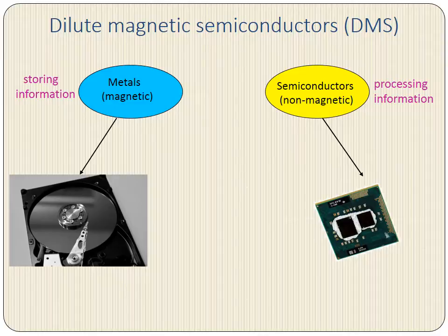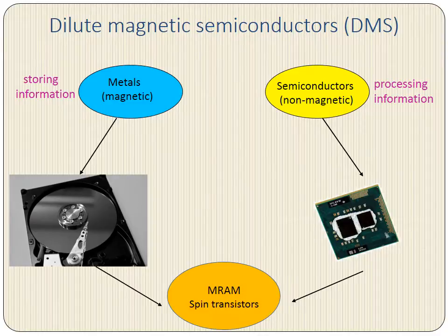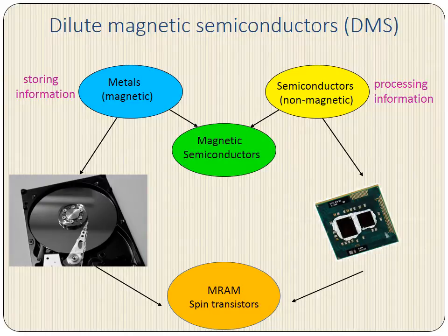Now, to date, we have typically kept these two classes of materials separate within our consumer products. But there is hope to combine them to form new and novel devices, such as magnetic random access memory and also spin transistors. It should be noted that there's been a little more success in creating MRAM over viable spin transistors. However, integrating magnets and semiconductors hasn't been straightforward. A fundamental obstacle has been the impedance mismatch between these material classes, which will destroy your spin polarization. Now, one common solution is to place a resistive barrier at the magnet and semiconductor interface, but this does have the overall drawback of limiting your current. Now, another solution is to get around this impedance mismatch entirely by using magnetic semiconductors, and it turns out that these may be the key ingredient to achieving this synthesis.